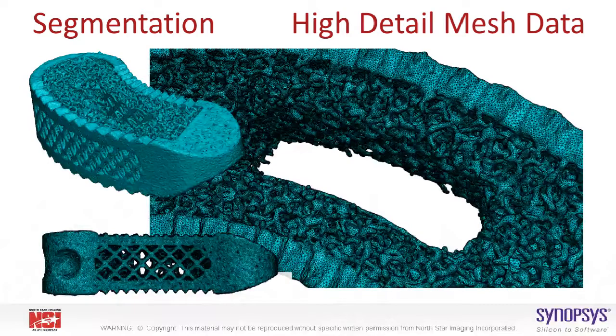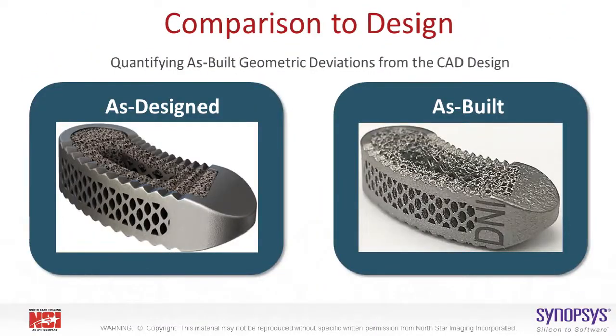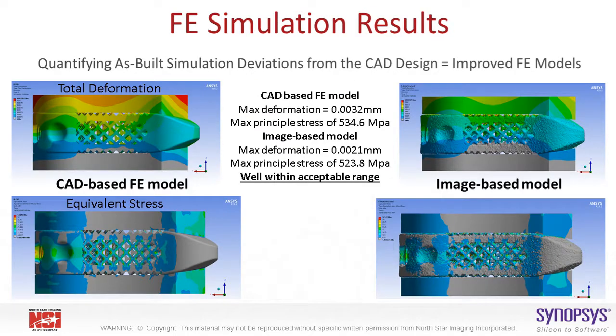This slide is just an example of the high detail surface mesh data that can be generated by the Simpleware software. By CT scanning the as-built sample, we can compare the printed part to the original CAD to compare any geometric deviations from the design. We can then enter that as-built data back into the finite element simulation model to see what the impact will be. When we compare the FE simulation results from the image-based model to that of the CAD-based model, we can see that the max deformation and the max principal stress results were well within the acceptable range. So that shows that the CAD-based model wasn't too far off from the actual printed part, but this allows us to provide an improved FE model for the printed parts going forward.